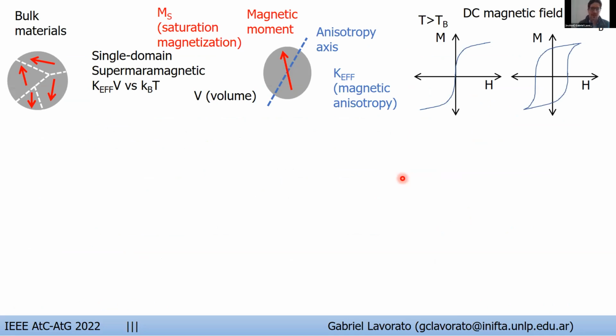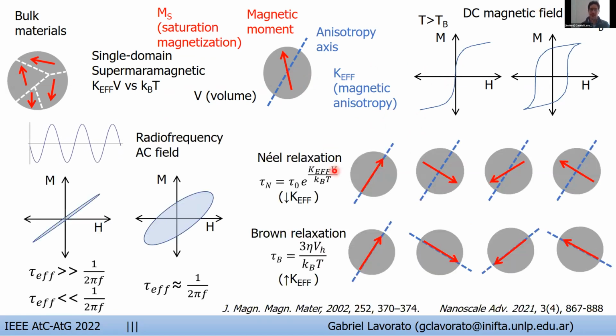Compared to bulk materials that are organized into magnetic domains, nanoparticles below a certain size are single domain, and their properties are defined by their volume, the magnetization, and the effective anisotropy. When the anisotropy energy is similar to the thermal energy, the response of these particles is superparamagnetic, and under DC magnetic fields, we will find no coercivity at temperatures above the blocking temperature. Under AC magnetic fields, the magnetic moment of the particles oscillates, trying to follow the field, and some energy is lost as a consequence of this process, which is released as heat.